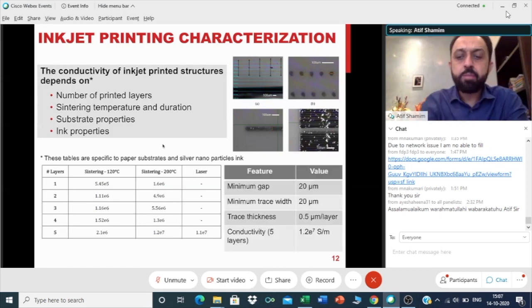substrate, that you could get conductivities which are of the order of close to the bulk metals. Like for example, copper, silver, gold, they are like 5 into 10 per 7 Siemens per meter. We were getting around 1.2 or 2 into 10 per 7 Siemens. So this was very encouraging because you could get conductivities of the metal close to that. The minimum gaps or feature sizes which we could get from those printing was like 20 microns.